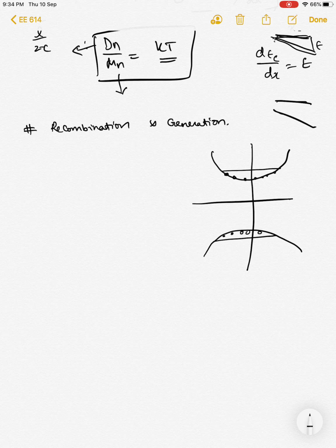The thermal energy is enough for an electron to be excited from the valence band to the conduction band, and we know that the gap in the energy is Eg, called the energy gap, which is the smallest at this particular point. Now if an electron in the valence band having an energy E and wave vector k, these being the two things which determine at which point it is, has to be excited to the conduction band at energy E prime and k prime, they have to have this particular relationship where E prime is E plus some constant.